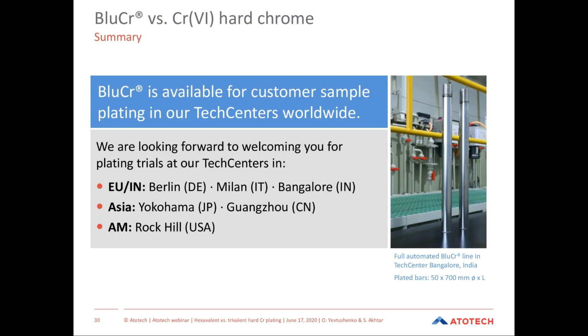On slide 16, where there were calcium chloride samples plated, were those samples plated with nickel strike layers? Slide 16, I guess this is for calcium chloride. No, these parts were not plated with nickel strike. So this is semi-bright nickel and BluCr on top.